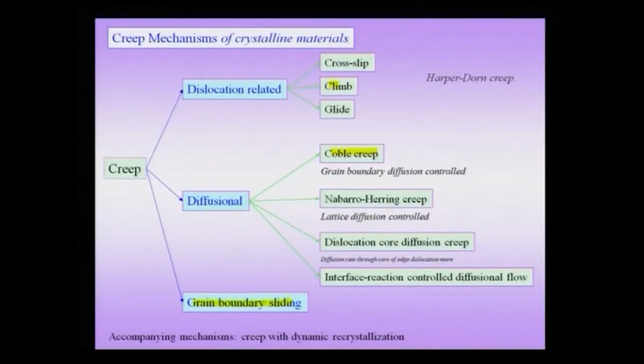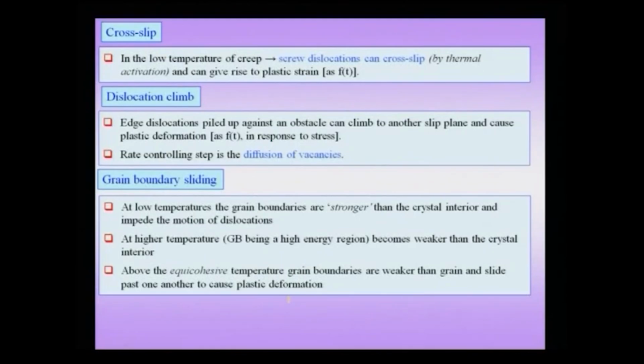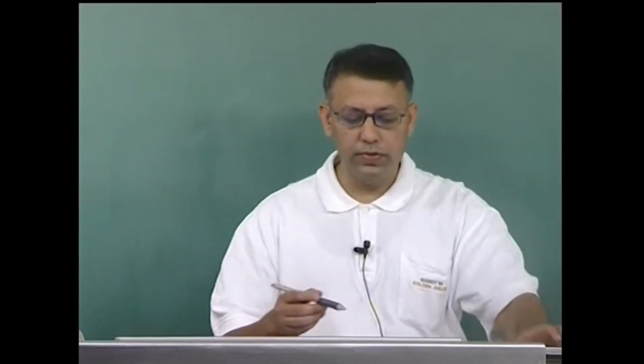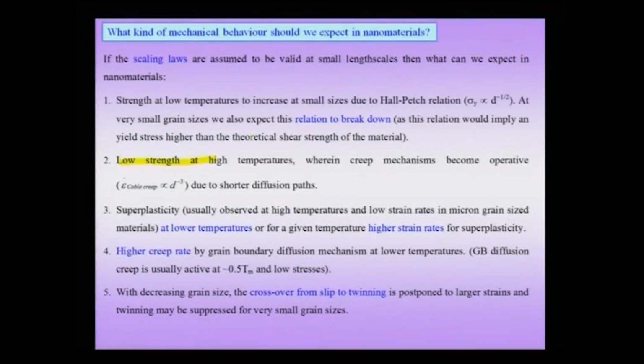Additionally, we also noted that one of the important mechanisms of creep is grain boundary sliding, and for grain boundary sliding, in some sense we have to cross the equicohesive temperature. Decreasing the grain size is in some sense like increasing the temperature, and therefore even at low temperature we would expect increased creep rate. That means we would expect high creep rates in nanomaterials, and that too at lower temperature. So, this is what we had anticipated.